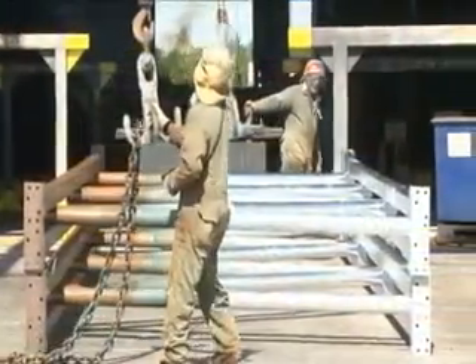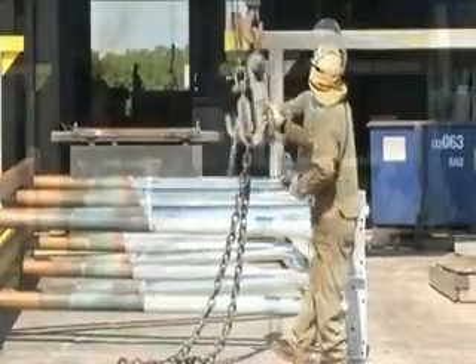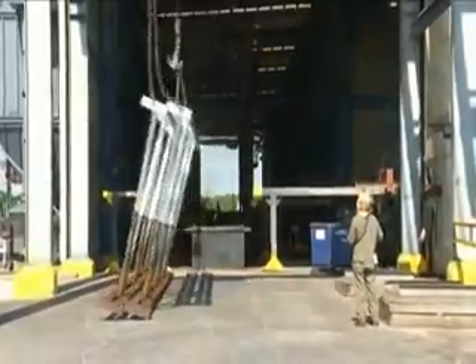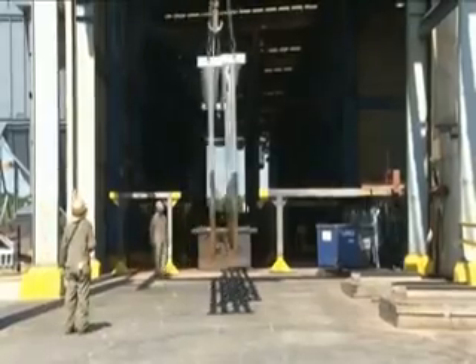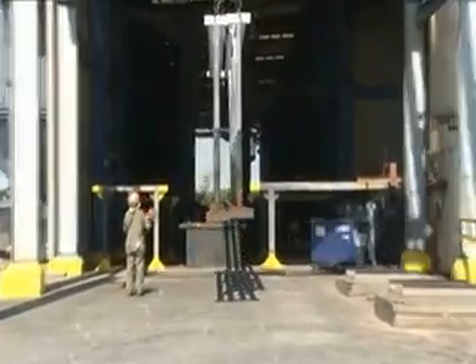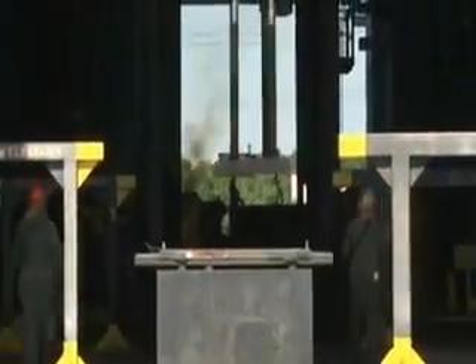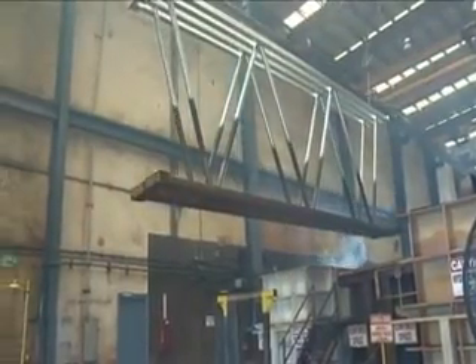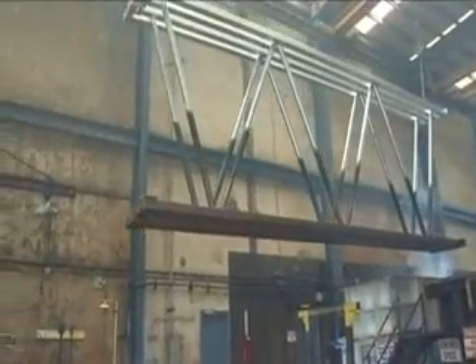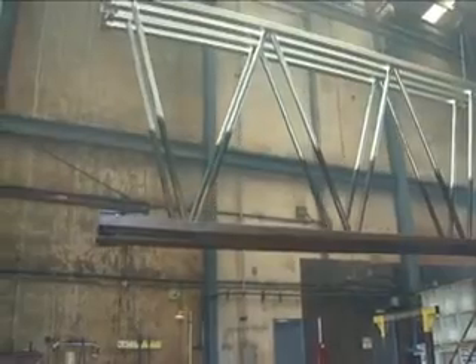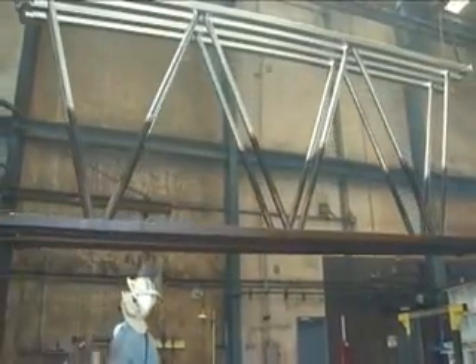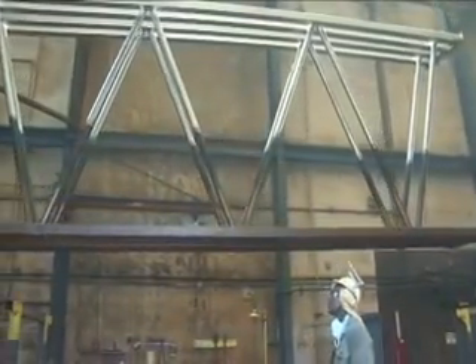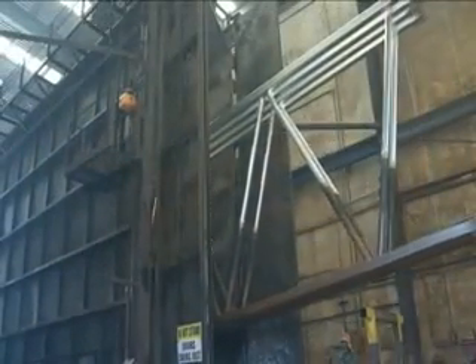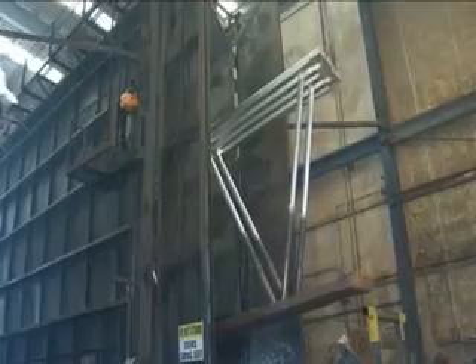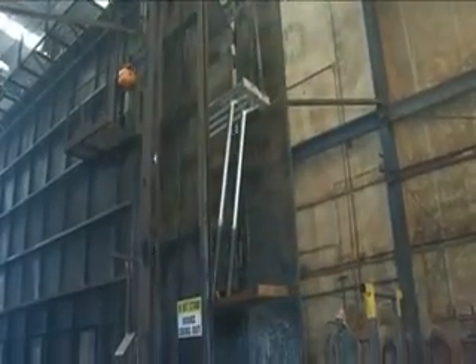Since the huge trusses are too big for the tank, they're then flipped over and wheeled back through the plant for a second dip. What it will do is go all the way back through the system into the processing tanks, because you see how the bottom has already begun to rust, so it'll go back into the acid, begin to pickle that side of the steel again. It won't take very long because it's already been pickled once. That's just a flash rust on it. So that'll pickle off, it'll rinse, back to the pre-flux, and then back to the kettle.